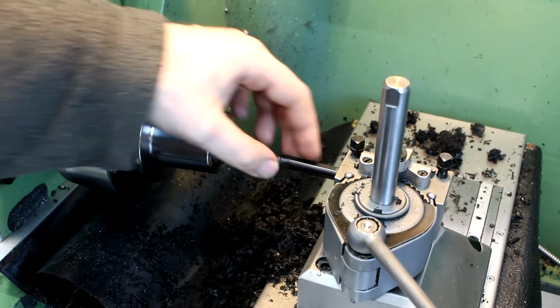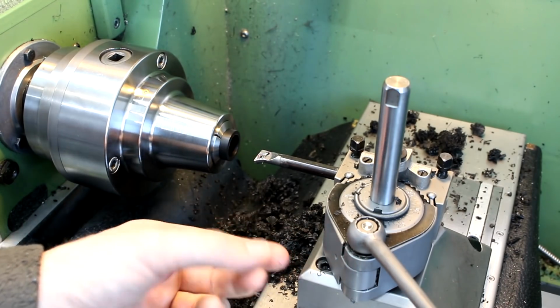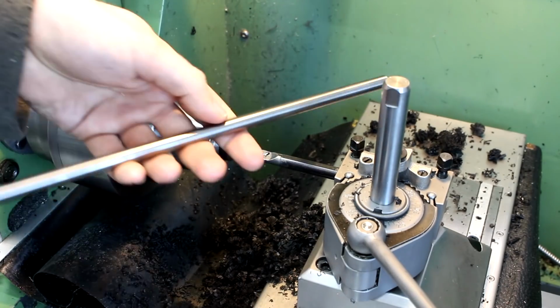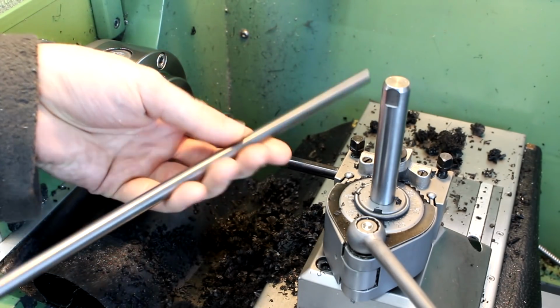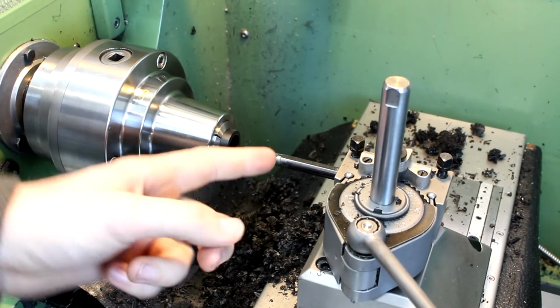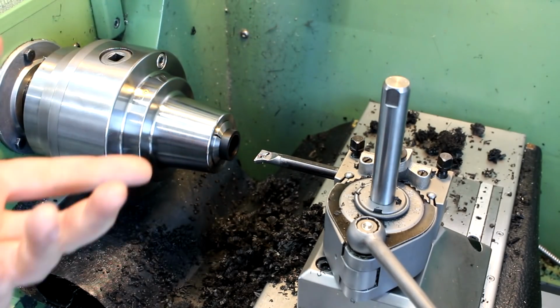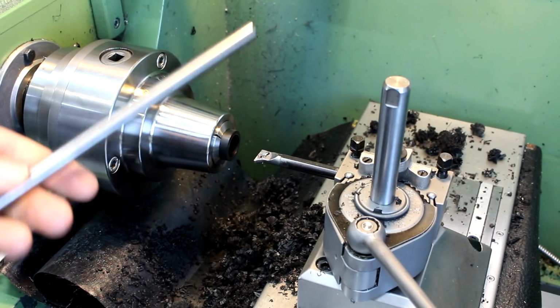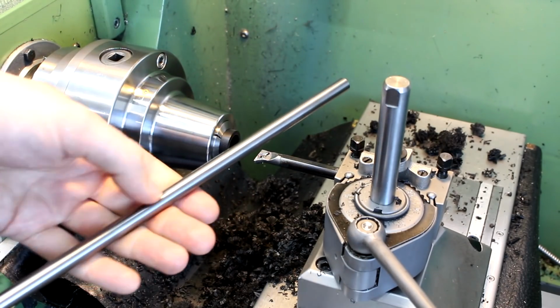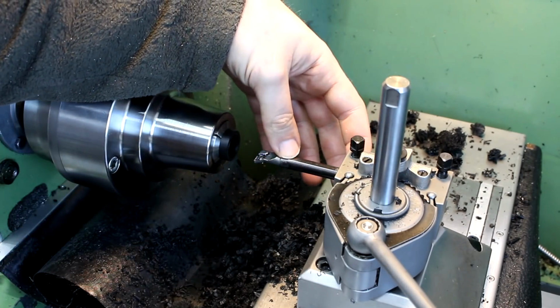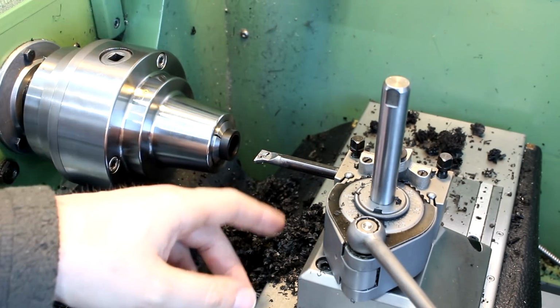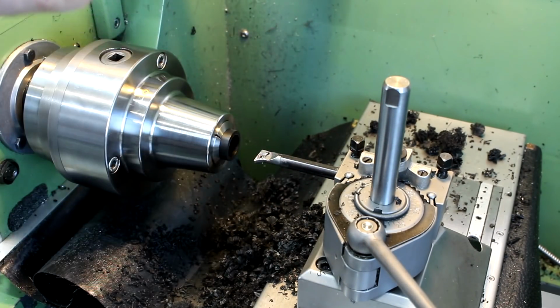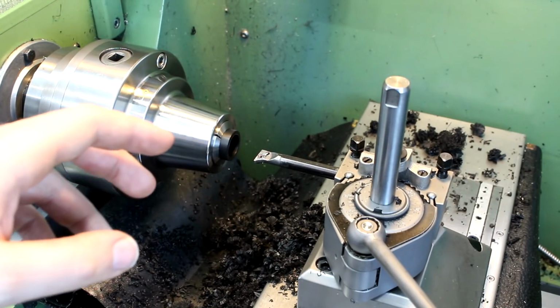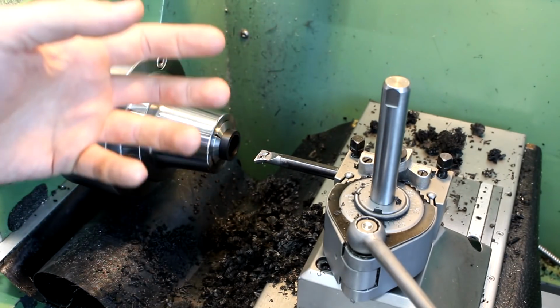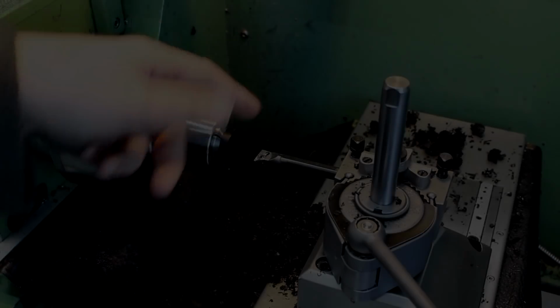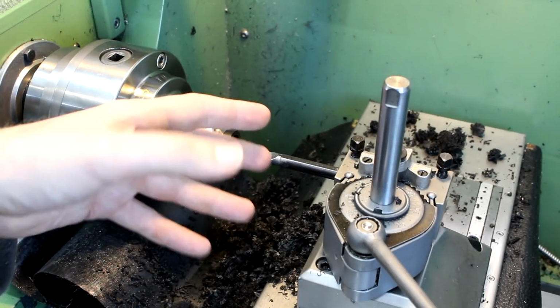So my idea was to take this boring bar, chop it off, take a piece of 10 millimeter carbide, your regular solid tungsten carbide that's also used to make cutters, and silver braze a carbide shank onto it. The idea behind that is the modulus of elasticity of tungsten carbide is about 3 times higher than steel. It doesn't matter if the steel is hardened, soft, or stainless or tool steel. Steel always has the same modulus of elasticity, no matter the condition. That means with the same load applied to the cutting edge here, the deflection will be 3 times less.